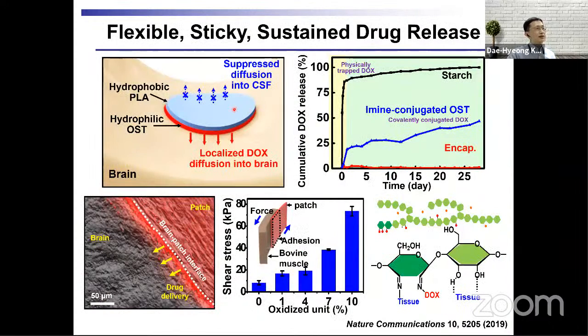And the device was thin enough to be flexible and make a good conformal contact. This image shows the magnified view of the interface between the patch and the brain. We can see the very good conformal contact. Also, since we included oxidized units in the starch film, it could make a good adhesion to the brain tissue. Also, it could make conjugation with the doxorubicin molecules, while some doxorubicin molecules are still physically trapped only. And that conjugation is helpful for long-term sustained drug delivery.